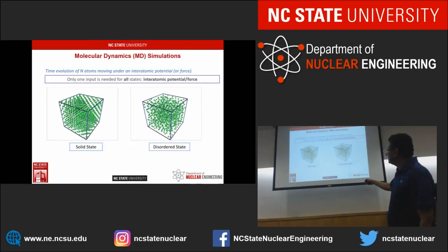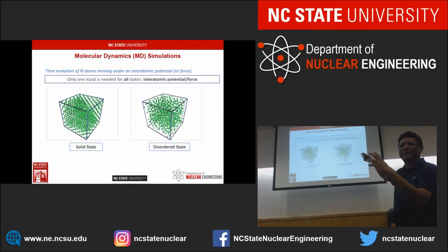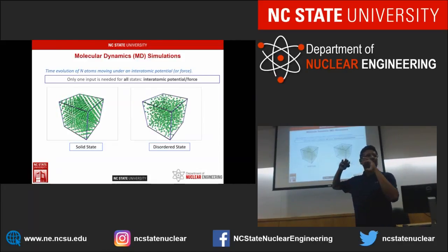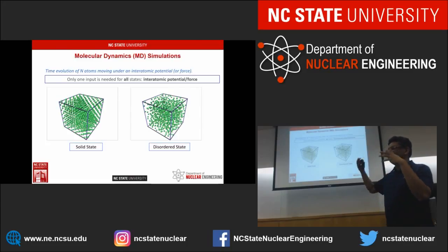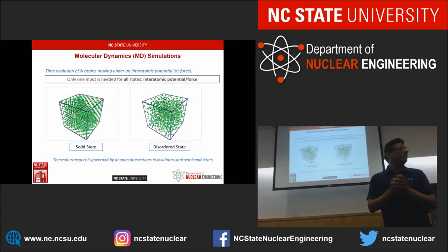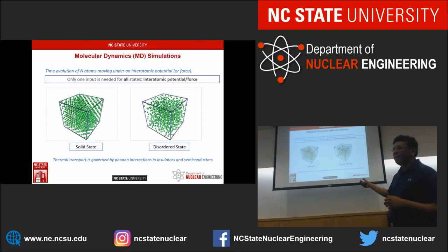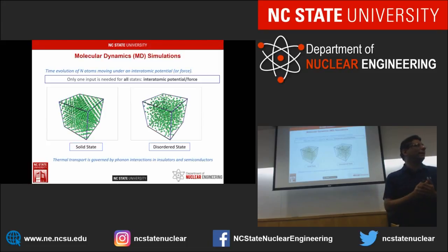If you look carefully at one of these atoms, you can see it vibrating back and forth. But if you look at the whole set of atoms from afar, you can see a kind of wave-like motion. We can study all that interesting physics. Those atomic modes are normally called normal modes, and normal modes are important because they are closely related to phonons — quantized lattice vibrations. Thermal transport is actually governed by phonon interactions, especially in insulators and semiconductors.